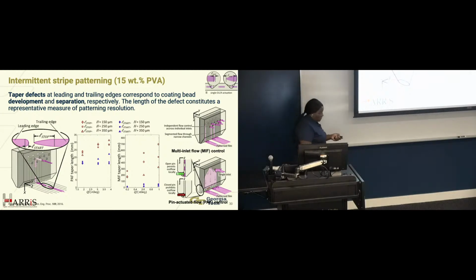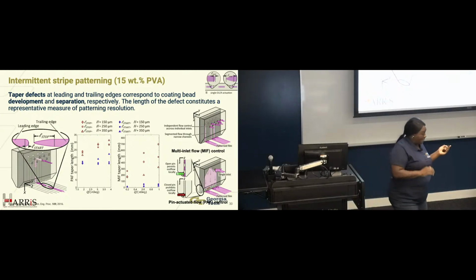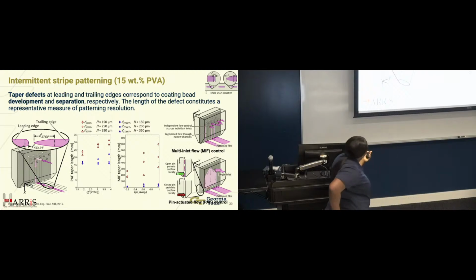So going a little bit further, if we now take a step back, we have this single material that we're coating, and we're taking it on and off. We have our leading edge, our trailing edge. We want to stop very quickly. So this one is being fed through the orifices, and then this one is actuated at the base. What we show here is that depending upon how the fluid is flowing in, we get more or less taper in terms of the length of the taper. So that trailing edge is more prominent whenever we use MIF, and it's less prominent whenever we use PAF.